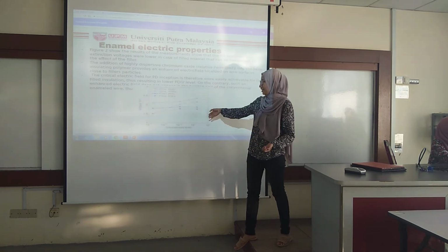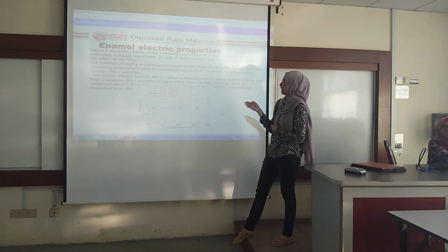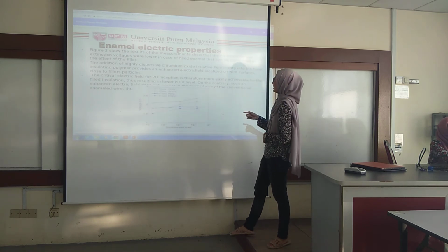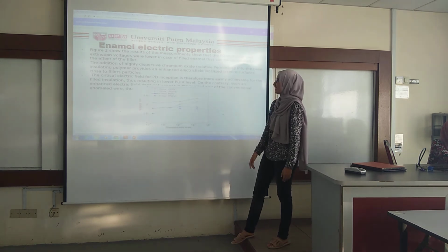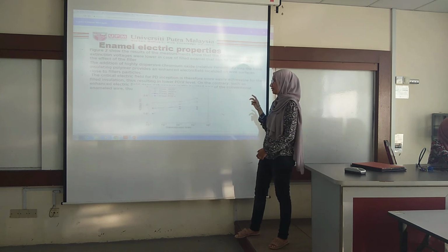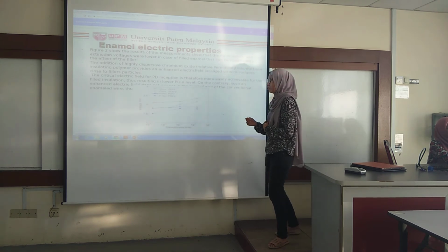For the enamel electric properties, as shown in figure 2, the result of the measurement shows that the PD inception and insulation voltage were lower in the case of pure enamel. That can be considered as the effect of the filler. The addition of highly dispersive chromium oxide into the base insulating polymer provides an enhanced electric field localized on the wire surfaces close to the filler particles.